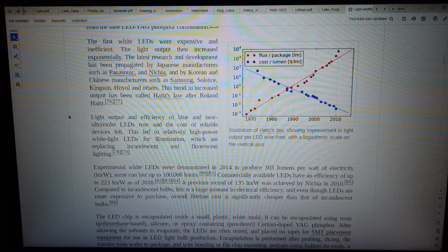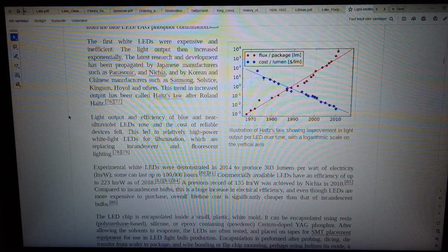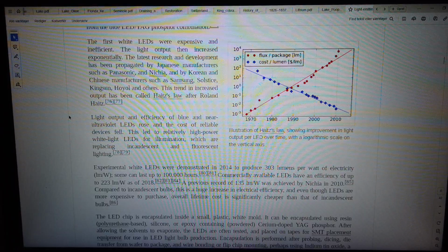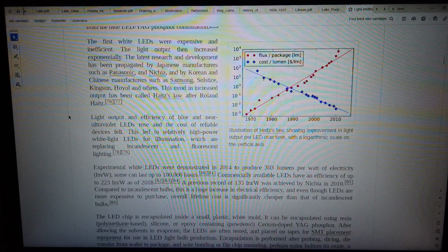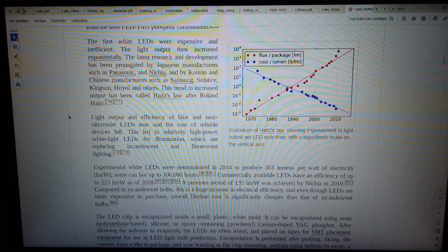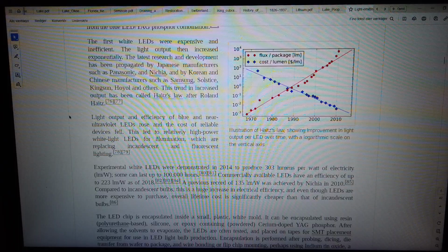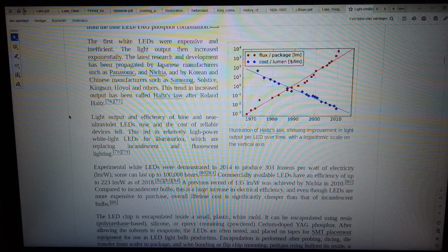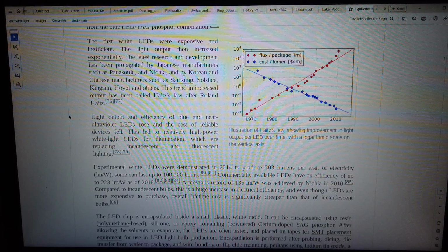80, 81. Commercially available LEDs have an efficiency of up to 223 lm/W as of 2018. 82, 83, 84. A previous record of 135 lm/W was achieved by Nichia in 2010. 85. Compared to incandescent bulbs, this is a huge increase in electrical efficiency, and even though LEDs are more expensive to purchase, overall lifetime cost is significantly cheaper than that of incandescent bulbs.